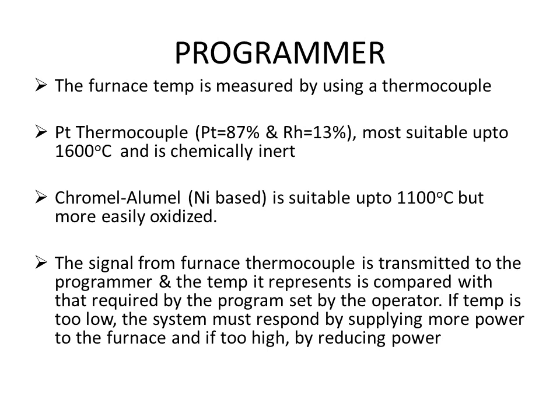Another part of thermobalance is the programmer. To measure the temperature of the furnace, we require some sensor, and for this purpose thermocouples are used. So here are a couple of thermocouples mentioned over here. First one is platinum thermocouple. This is actually platinum 13% rhodium thermocouple. Means there is 13% rhodium and 87% platinum. And this thermocouple is most suitable up to 1600 degrees centigrade. Another advantage is it is chemically inert. Another thermocouple is chromel aluminum thermocouple, and this is the nickel based thermocouple. It is suitable up to 1100 degrees centigrade, but the problem is it is more easily oxidized.